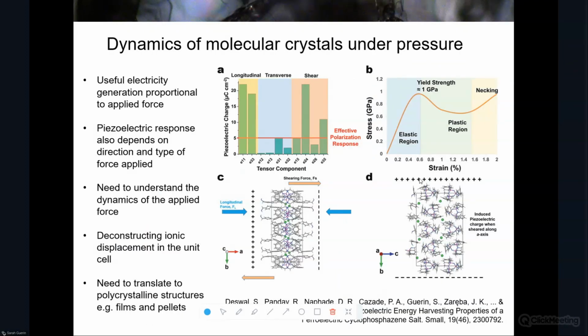Then going on to ferroelectricity. This is a study with Professor Bhumi-Shankar's group, where we looked at quite a large ferroelectric molecular crystal. We could look at, again, the remnant polarization in different directions. We could also in silico calculate our stress strain curve and look at our elastic and plastic region to determine how much ionic displacement would take place. And again, look at what the actual bonding patterns and supramolecular packing tells us about piezo and ferroelectricity in these materials. So we were able to directly relate our single crystal density functional theory models to the macroscopic polycrystalline devices that the guys were making and measuring the output electricity from.